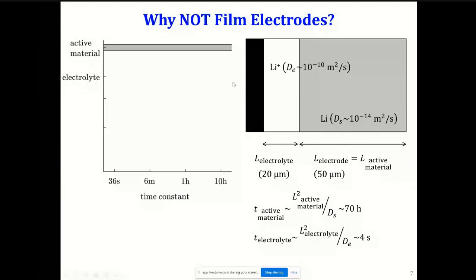So on this plot, the time constant for lithium diffusion turns out to be much higher. Now, one may look at it and say, oh, that's wonderful. That means I can use my phone battery for 70 hours. That may be true, but it would also take about 70 hours to charge it. So it's not a feasible situation. The reason these film electrodes would be limited is purely because the solid state diffusion is so sluggish.